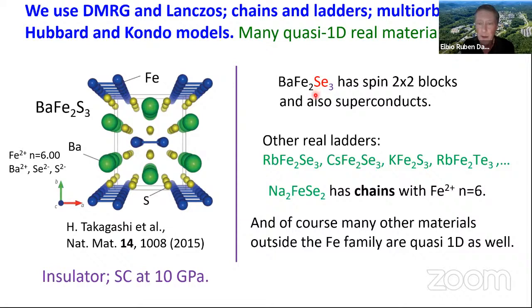There are many other compounds of the same family with a different chemical composition. The one with selenium has a very exotic spin arrangement. I will discuss that in just a minute. And they also superconduct with pressure. There are chains now that have been reported with the valence of 2+. That's important because in general, the chains with iron have a valence of 3+. And that sort of is a special case. But with the 2+, it is the same family as the iron in the planes and the ladders.